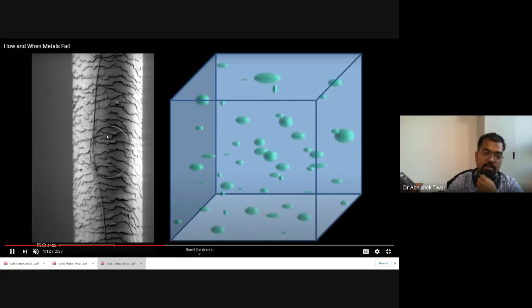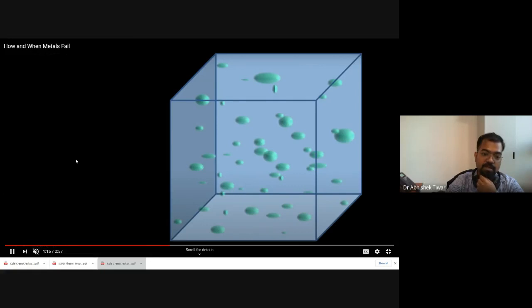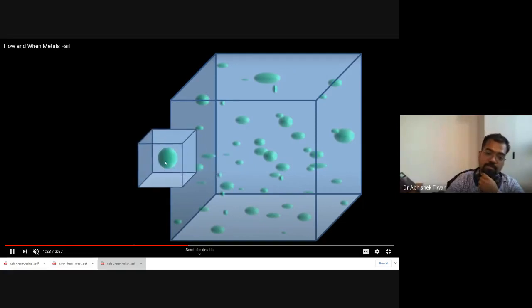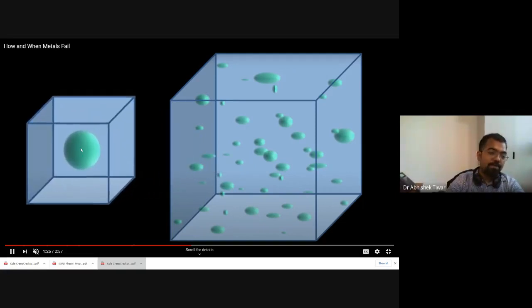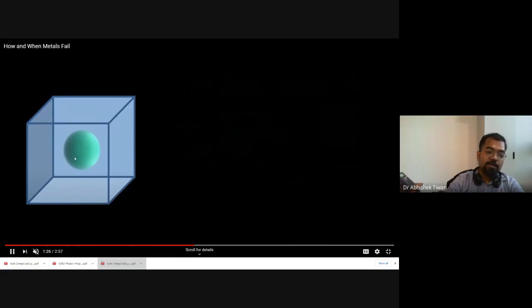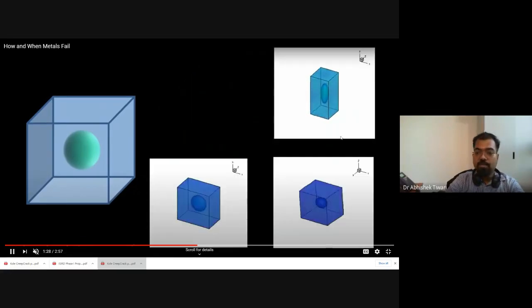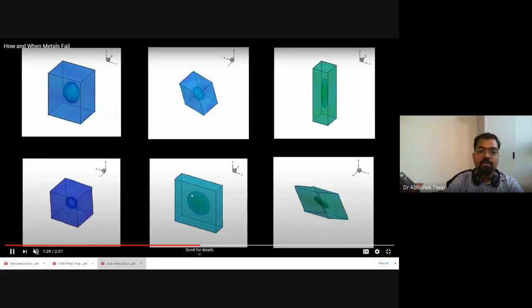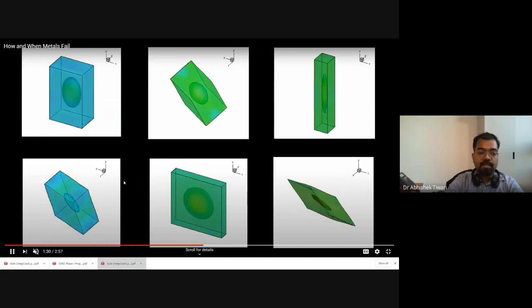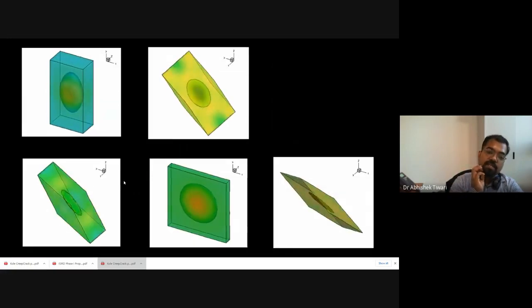Right? And so this is the surface of the specimen, which, once we have a lot of cracks on it, looks like that. So what this person has done, or is proposing, is that you take a small piece of this part. This already is a small piece of the whole specimen. From this part, again, you take a small piece where you assume that there is only one void in the system, and then you apply load on it. You can apply different types of load, compression, tension, shear, and you find out how this thing will deform if there is a void inside the material.